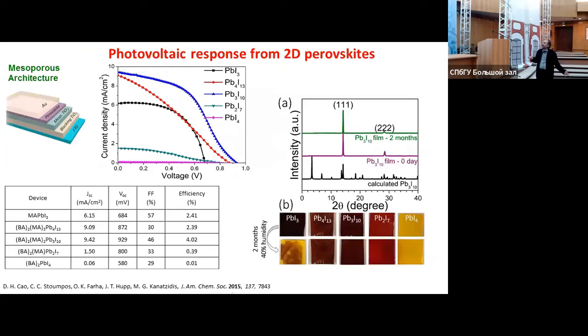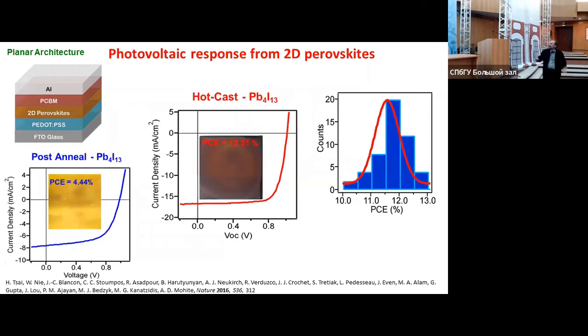And we did make devices. Originally, we didn't get such good devices, I must admit. It was the mesoporous architecture that we used. We got up to 4% for the 3 layers. But then, again, we collaborated with the group of Aditya Mohite at Los Alamos.